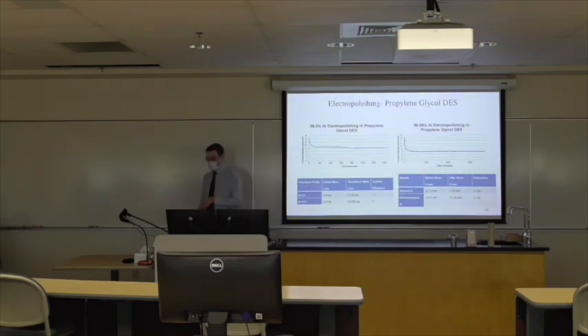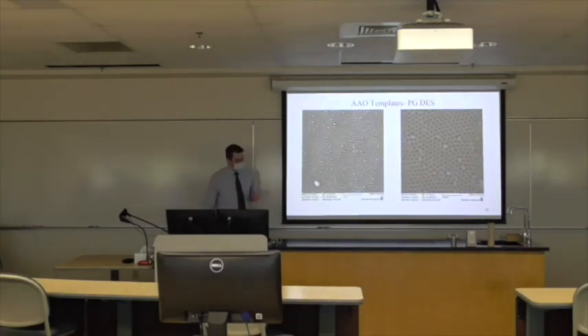And that was done for the dissolution of the oxide layer in between the two steps. Instead of using chromic acid, we used 2 molar phosphoric acid, which requires a little bit more care because it could be damaging to the aluminum if you let it go indefinitely, which you don't see as much with chromic acid, but it is significantly better than chromic acid as far as environmental concerns, being simply phosphoric acid. So, with those conditions in mind, we're able to use our propylene glycol electropolished system to make aluminum oxide templates. And these are the results that you get from it.